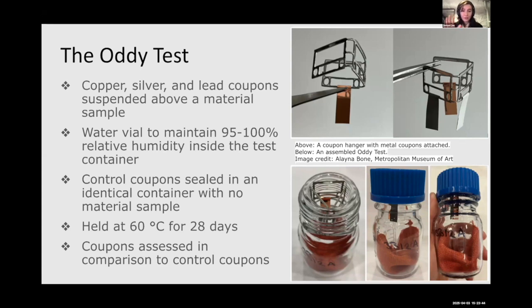The high temperature and relative humidity inside the assembly accelerate the potential off-gassing of the material, and an identical container with three metal coupons but no material sample serves as a control. After 28 days, the metal coupons are assessed by a trained practitioner in comparison to the control coupons, and a rating is assigned to the material based on any observed changes to the metal coupons.